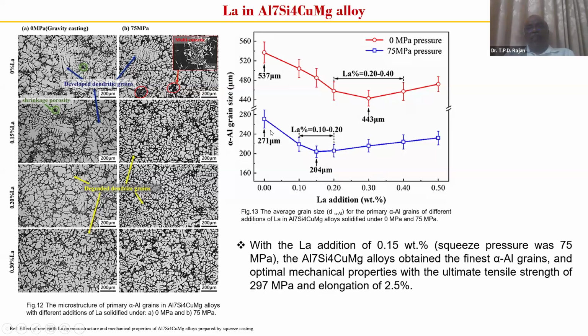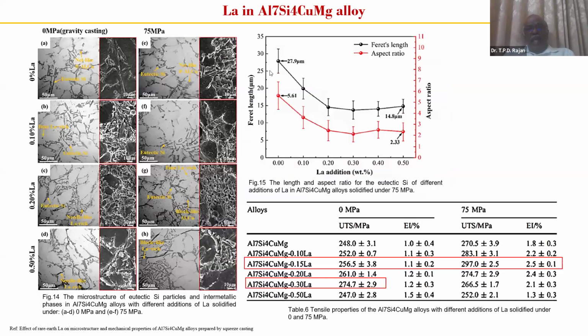And in the case of squeeze casting, with the application of pressure, we can see that it's almost 204. So the combination of the addition of lanthanum with the application of squeeze pressure up to 75 megapascal shows a reduction of the grain size. This reduction in the grain size again enhances the mechanical properties of the alloys. Here we can see that the mechanical properties of the alloys increased to 274 when compared to the other alloys with 0.3 percent of lanthanum addition.